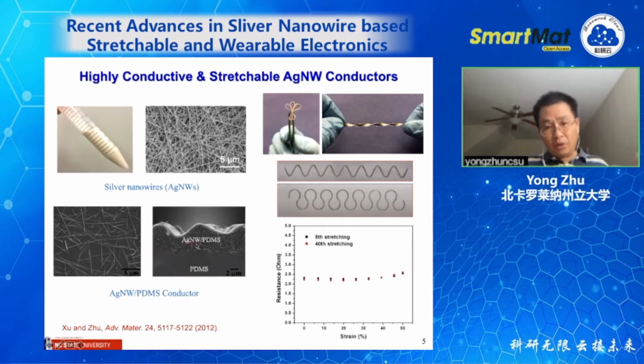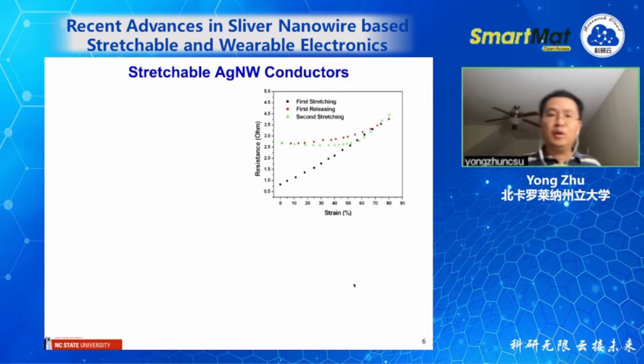This composite layer is highly conductive, and there are different ways to print it and so on. You can see the resistance versus the strain. Resistance is nearly independent of strain. You can stretch multiple times, but it's independent of strain. So that's really an ideal stretchable conductor. You want to maintain a constant resistance. But I want to talk a little more about the mechanism of this stretchable conductor.